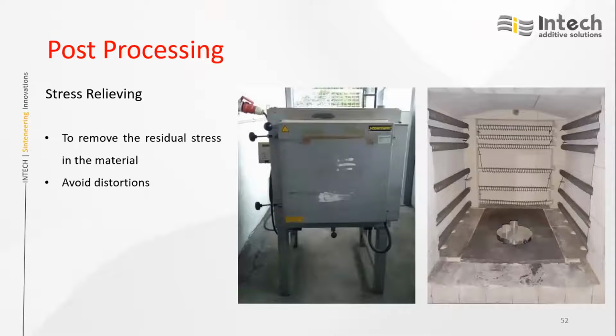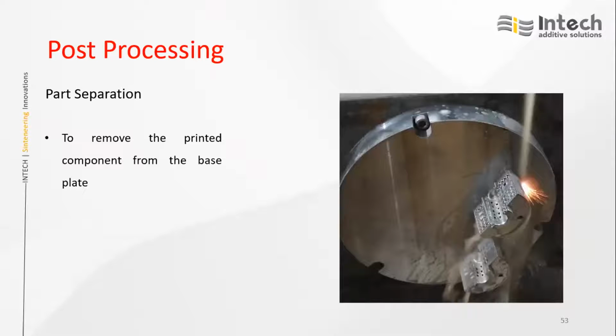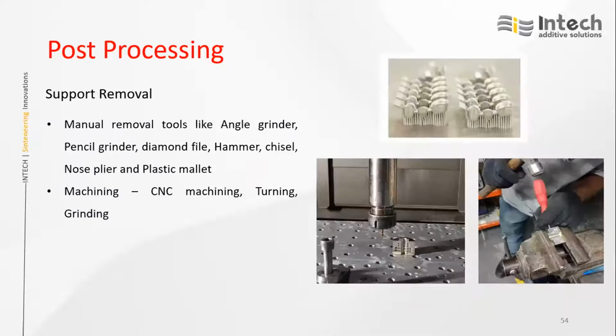Then we need to do stress relieving. Once the part is printed, in order to relieve the stresses, we need to put it into the furnace, and based on the material, we select the heat treatment cycle and relieve the stresses. Once that is done, we need to remove the component from the base plate with the help of wire cutting.